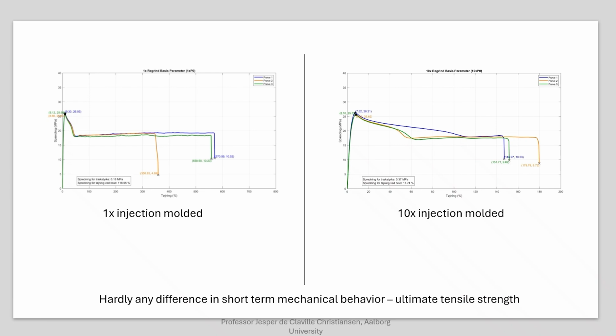So here are some results from real life. On the left-hand side, you have a polypropylene that has been injection molded once, and on the right-hand side, it has been injection molded 10 times. It might be difficult to see the actual values on these slides because the numbers are very small, but the yield strength, the top point of the two curves, is more or less the same. So it means that the tensile strength is not reduced in polypropylene after 10 times injection molding.